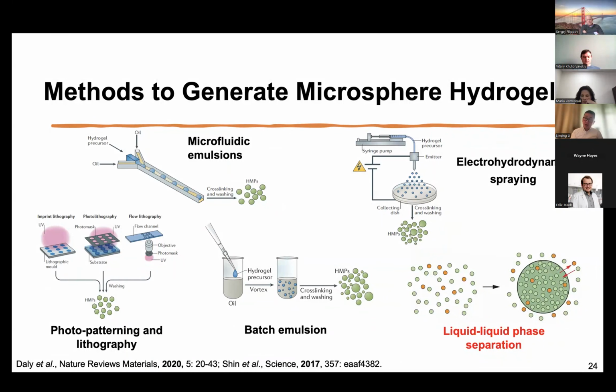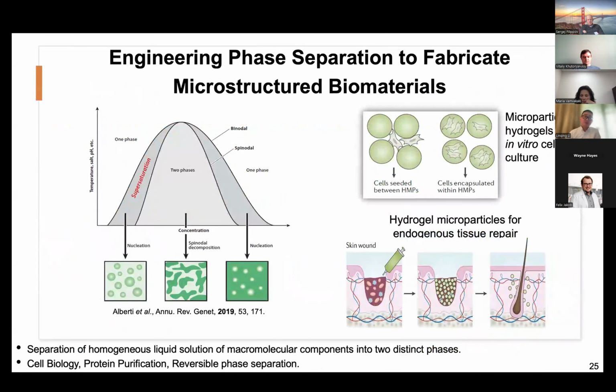So we utilize liquid phase separation as a way to create these phase-separated particles in our case. Liquid phase separation is a thermodynamically and kinetically controlled process. Depending on the concentration, you can generate nucleation or spinodal decomposition, forming continuous phases, or continue to increase the concentration and become reverse phases, controlled by the temperature, the solution pH, and the concentration. Of course, you can control either one phase or two phases. So there are a lot of parameters you can play with.